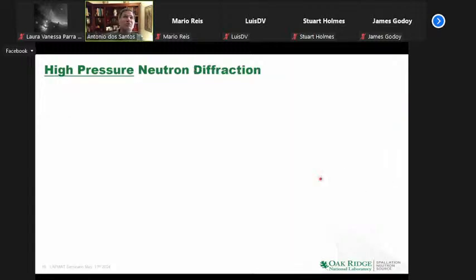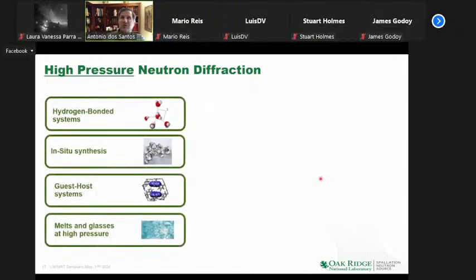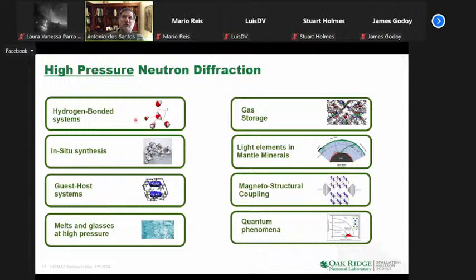But there are good reasons why we want to go that route, and I'll go a little bit forward here. Anything with hydrogen, hydrogen bonded, water, ice physics, methane, many clathrates, clathrate hydrates, any hydrogen bonded systems requires high pressure neutrons. To know when materials are made or why they're not being made requires in situ monitoring, and neutrons are great for that. Studies of guest-host systems, because the extended Q allows you to see the vibration of these guests in these cavities. So it's great. That extended Q also allows for the studies of melts and glasses at high pressure to replicate what happens in planets. This is then coupled to the isotopic sensitivity of these light elements in mantle materials.